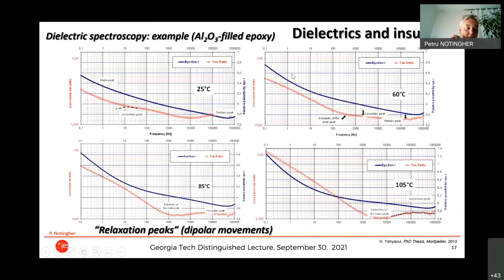And these are some examples. You see, for instance, on epoxy which is filled with alumina, this is a spectrum which starts at 0.1 hertz and ends at 1 megahertz. So we're not going to the frequencies where you see atomic or electronic polarization. This is the normal use for a material in electrical engineering. And you can see that here you have three peaks, one which is here, another one which is here, and you see that it increases, so you can imagine that there is another peak which is out of the spectrum. And when we increase the temperature, as the molecular mobility increases, the peaks will shift to higher frequencies.